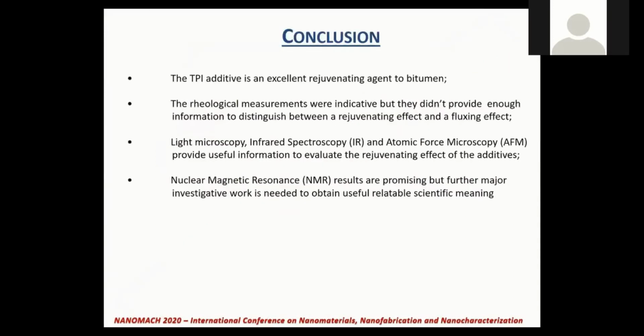In conclusion, the TPI additive is an excellent rejuvenating agent for bitumen. The rheological measurements were indicative, but they didn't provide enough information to distinguish between a rejuvenating effect and a fluxing effect. Light microscopy, infrared spectroscopy, and atomic force microscopy provide useful information to evaluate the rejuvenating effect of the additives. Nuclear magnetic resonance results are promising, but further major investigation work is needed to obtain a useful, relatable scientific meaning.